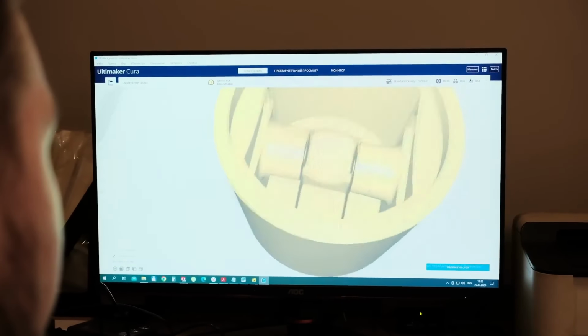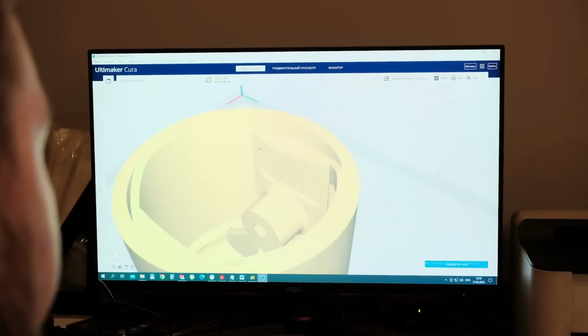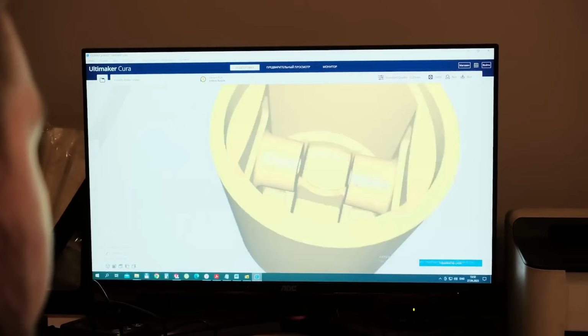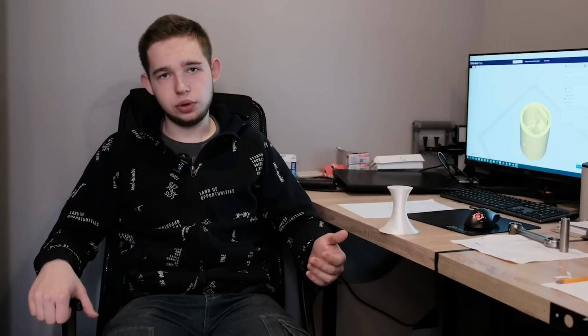What are the advantages of this technology compared to others, such as casting in a chill mold in molding sand or other methods? First of all, this technology imposes virtually no limitations on the geometry of the model. The only exception is channels with a diameter of up to 4 millimeters. Those are more challenging, but there are still ways to solve these issues. But overall, this technology doesn't have the same restrictions as, for example, casting in a chill mold or molding sand.